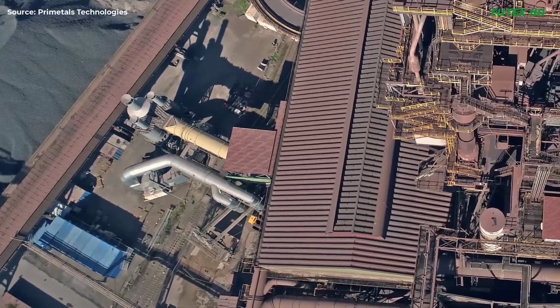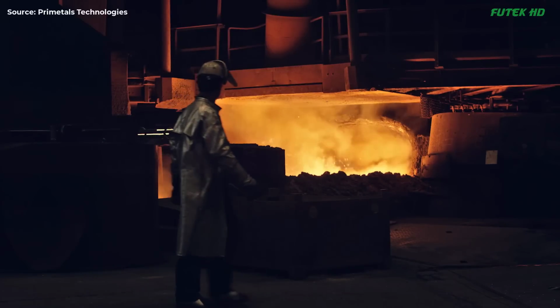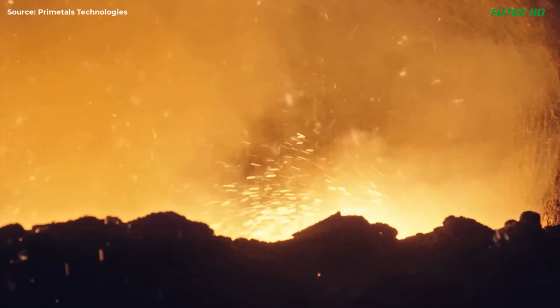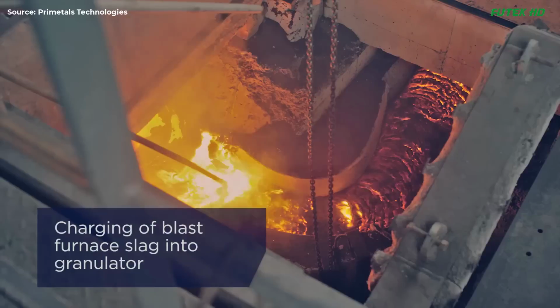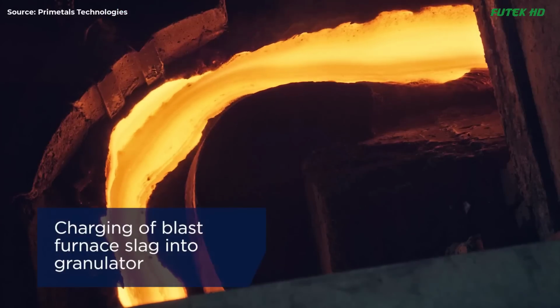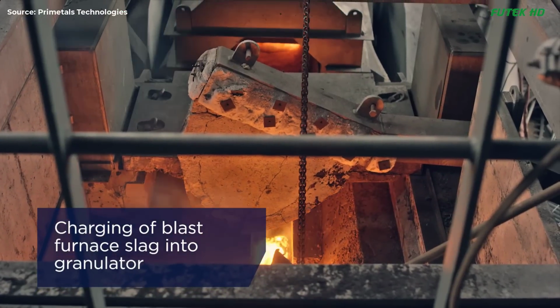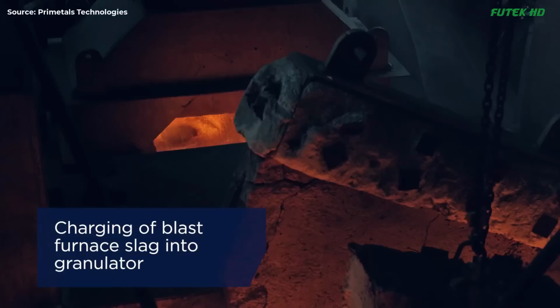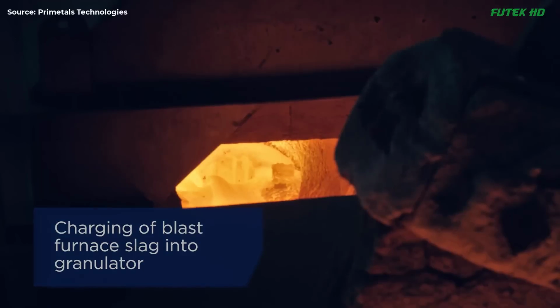In this process, molten slag at a temperature of 1,450 degrees Celsius is tapped from one of the blast furnace's 3 tap holes and directed into the granulator at a rate of approximately 1 ton per minute. The slag is then dropped onto a rapidly rotating disc, where it is granulated and cooled by an ascending airstream.